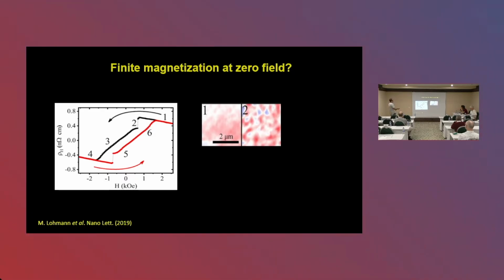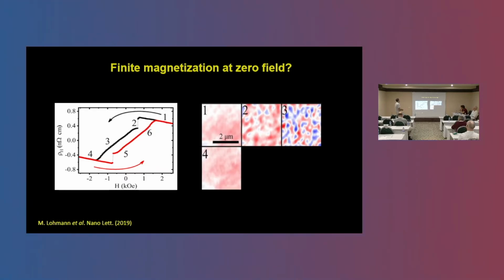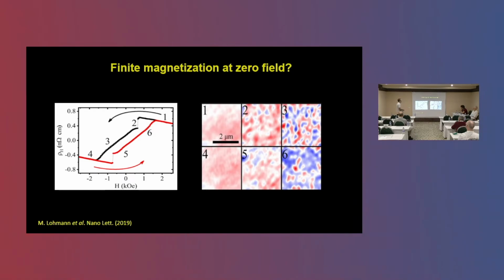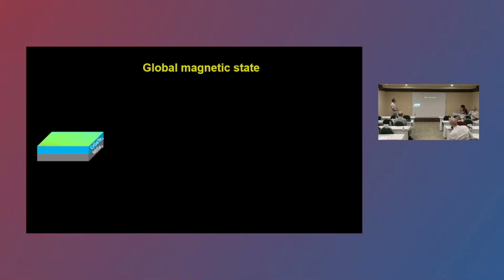At some point you get this step in the anomalous Hall signal, and this coincides with the appearance of some domains. Then you lower the field, you reverse the field, these domains seem to evolve, and then you again saturate the magnetization on the other side. This is also true for the lower branch. But the fact that they see a finite signal led them to think, okay, this material retains a finite magnetization at zero field. And we believe that this is not the case for at least most of the sample, but we'll talk about this in a moment.